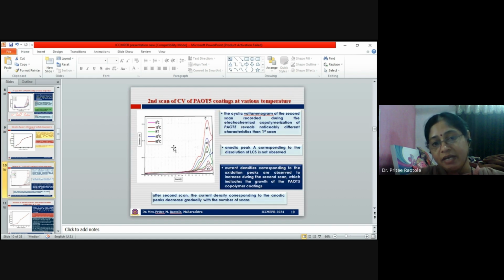This shows the second scan of cyclic voltammogram of PaOT5 copolymer coatings at various temperatures. The cyclic voltammogram of the second scan reveals noticeably different characteristics. The anodic peak A corresponding to dissolution of low carbon steel is not observed here. Also the current density corresponding to the oxidation peaks is observed to increase during the second scan, which indicates the growth of the PaOT5 copolymer coatings. After the second scan, the current density corresponding to anodic peak decreases gradually, which indicates the formation of noble coatings.